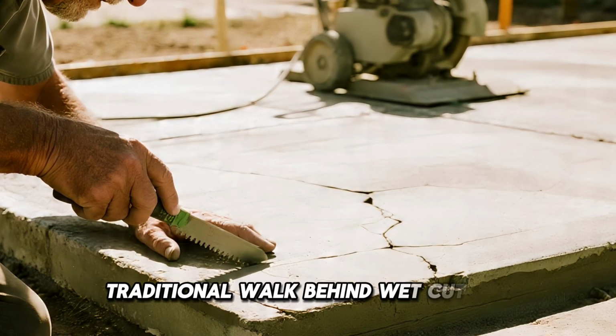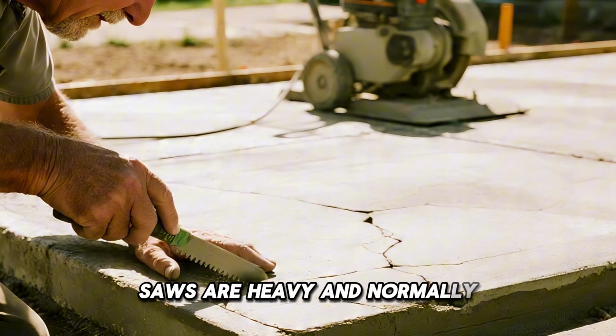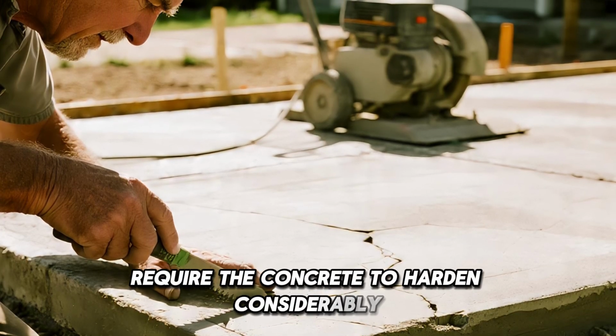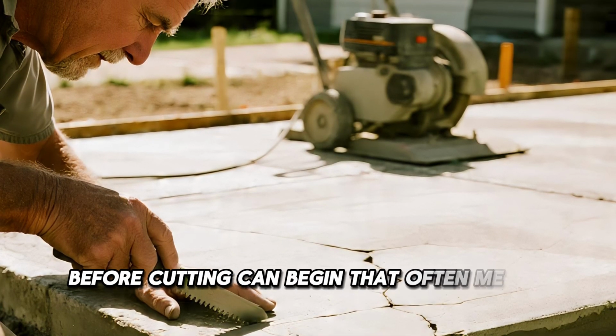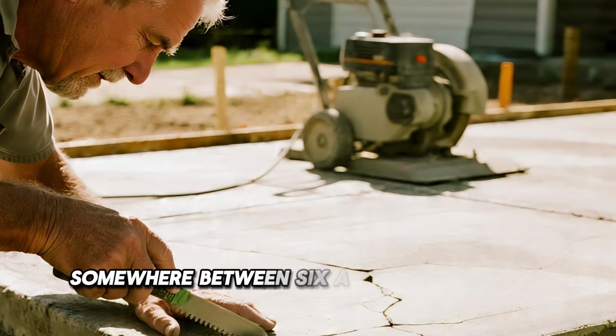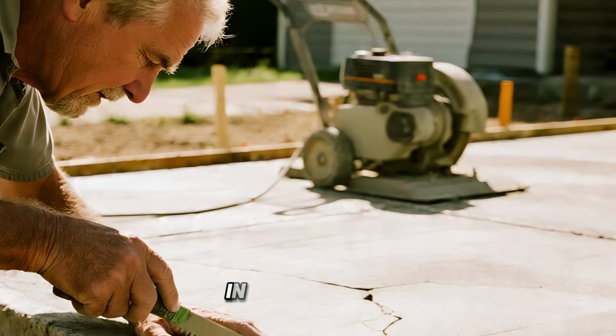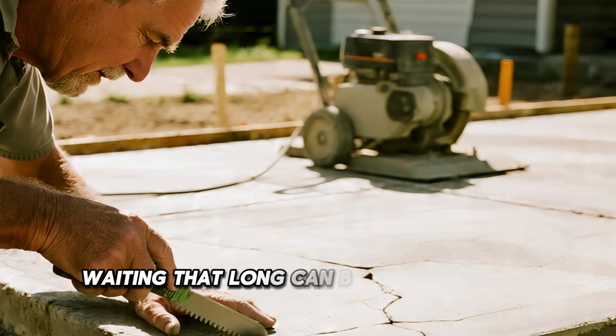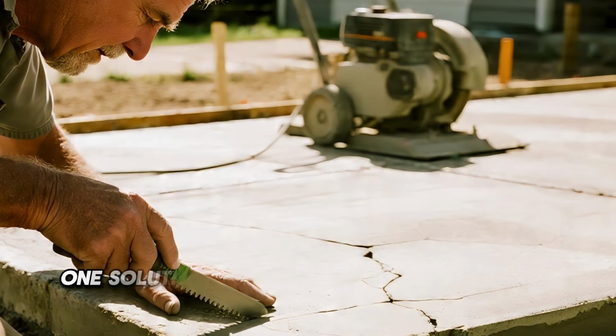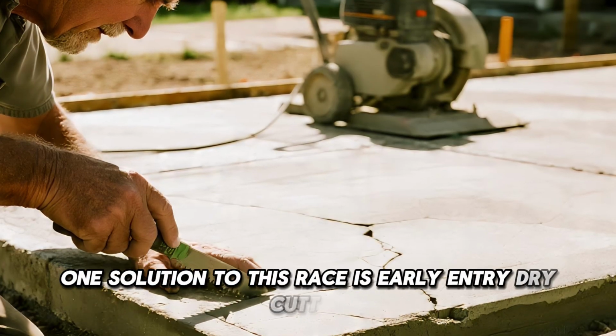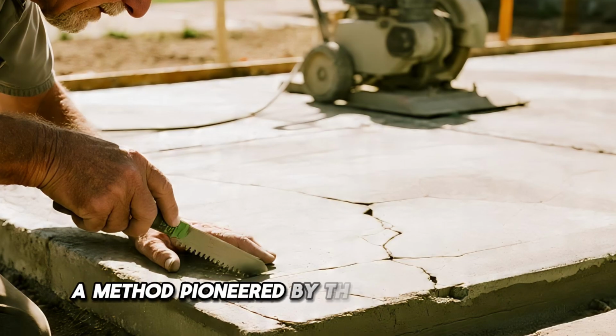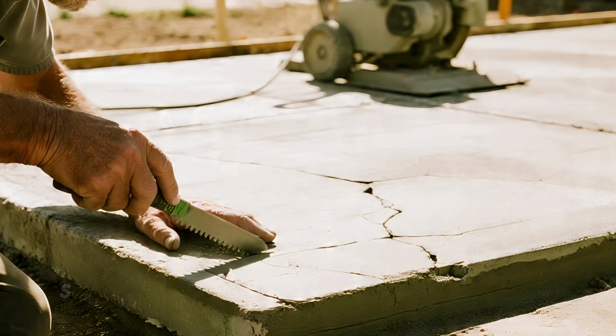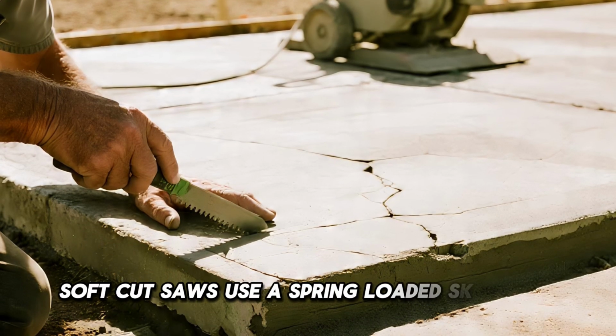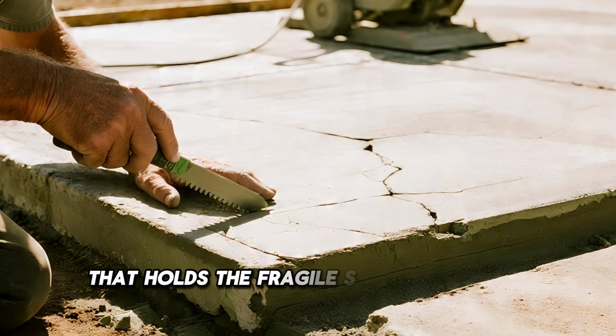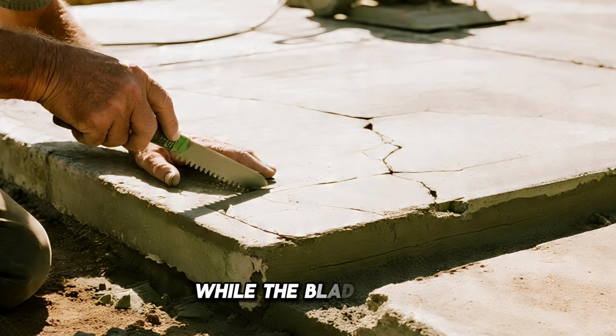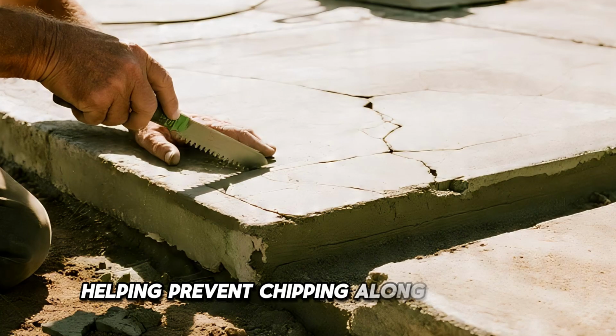Traditional walk-behind wet-cutting saws are heavy and normally require the concrete to harden considerably before cutting can begin. That often means waiting somewhere between 6 and 18 hours after the pour. In summer heat, waiting that long can become a serious gamble. One solution to this race is early entry dry cutting, a method pioneered by the Soft-Cut system. Early entry Soft-Cut saws use a spring-loaded skid plate that holds the fragile surface paste in place while the blade cuts, helping prevent chipping along the edges.